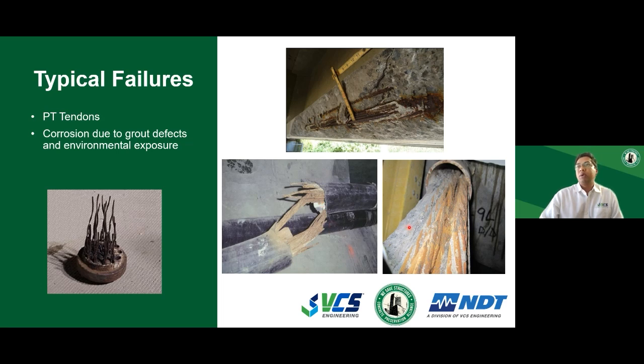In the bottom images, you can see the external post-tensioning system where you have obvious grouting defects or voids in the duct that have led to exposure of the tendons to the elements like moisture, chloride environments, or a lot of oxygen, which has resulted in the corrosion of the tendons. In some cases, the damage was so severe that it resulted in the tendons being completely severed, resulting in a complete failure of the tendon.